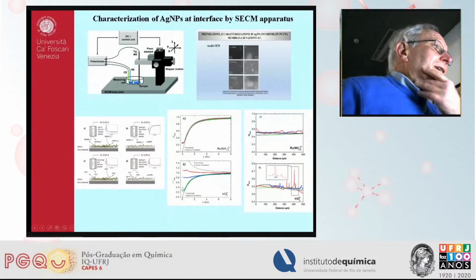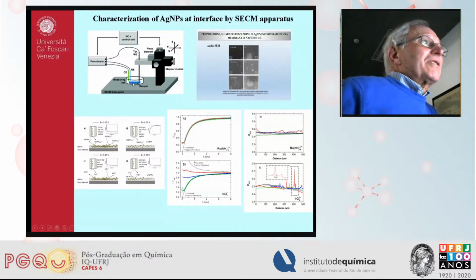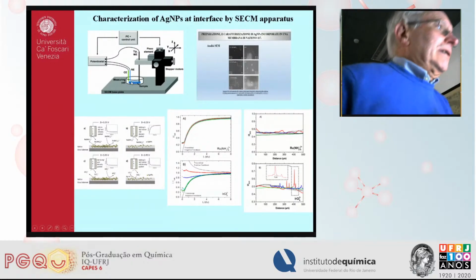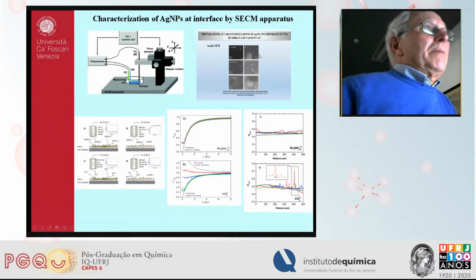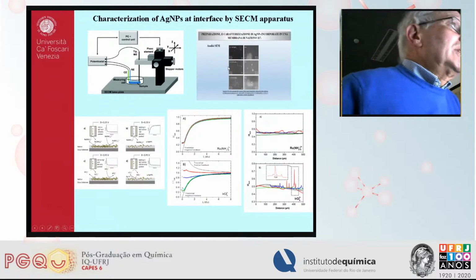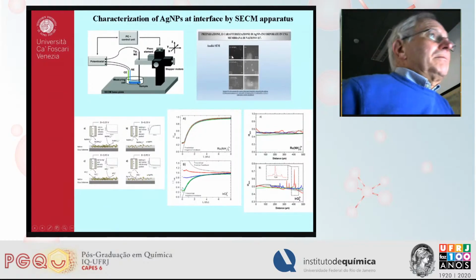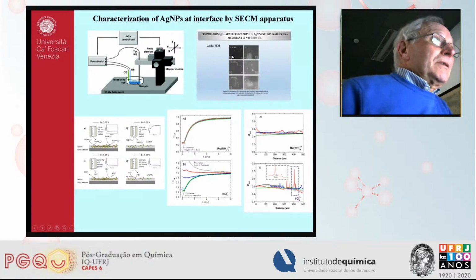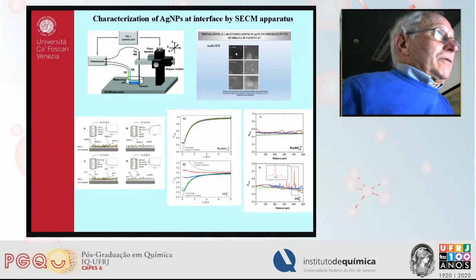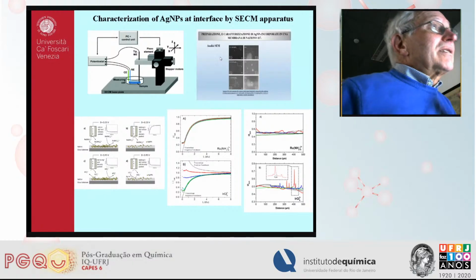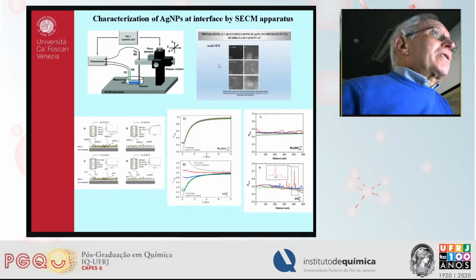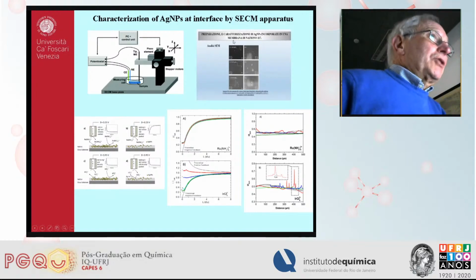So we use this technique to establish whether silver nanoparticles embedded, for instance, in a polymeric matrix like that shown here, are composed mainly of silver in the zero oxidation state, or silver in the presence of oxide, which means silver in the +1 oxidation state. Okay, so how could we establish this?